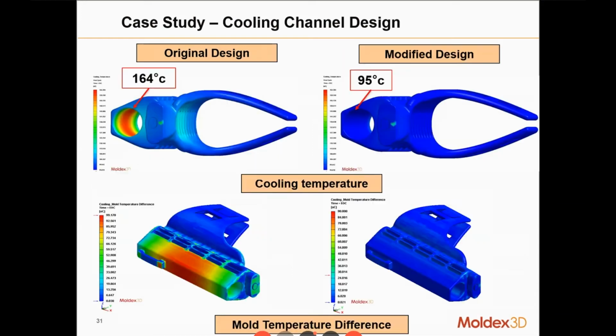It helps to remove the heat and decrease the heat accumulation. You can see the simulation result: the modified design has 95 Celsius degrees at these core regions, compared to the original design at more than 150 Celsius degrees.